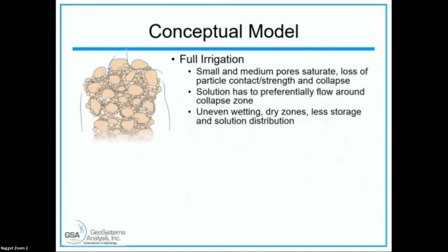So under full irrigation startup, if you do the calculations, what's happening underneath the emitter is, and I don't recall, but you're getting more than 100 times what your calculated irrigation rate is. So at 9 liters per meter squared per hour, you're actually applying more on the order of 100 over that little spot. So that's just pushing a massive amount of water into the leach ore.